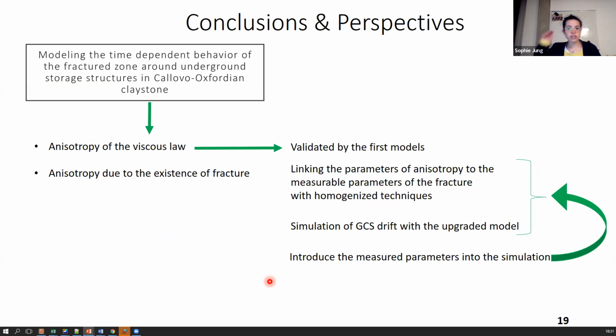So to conclude, many research teams are working on the modelization of the drift of the underground research laboratory. We have chosen a new angle as compared to the others by working on viscous anisotropy, and by assuming that this viscous anisotropy is due to the fracture. So we can say that the first model allows us to reproduce the convergence by working on the anisotropic creep behavior. So we sort of validate the fact that the anisotropy of the viscous law has a major influence on the convergence of the drift.